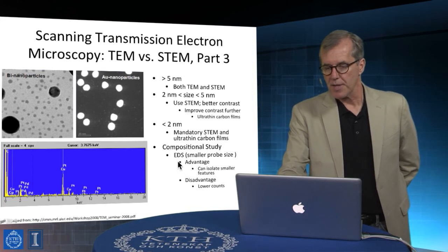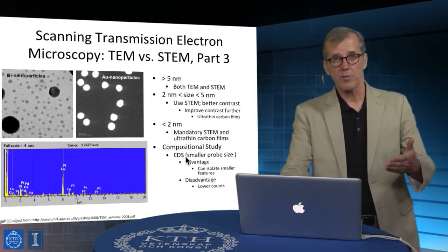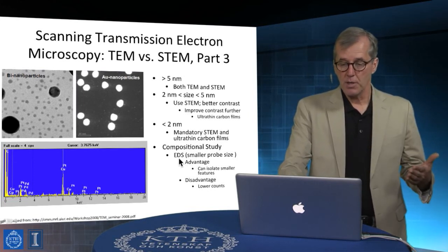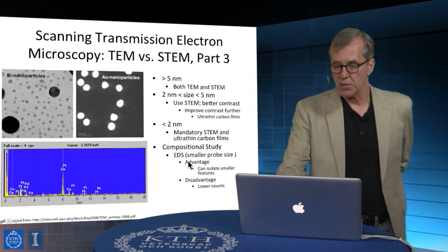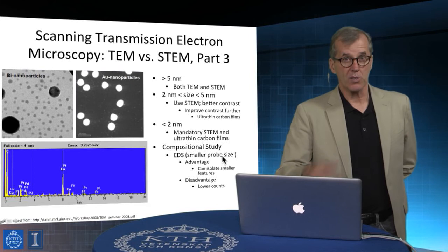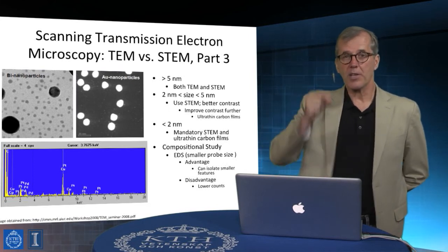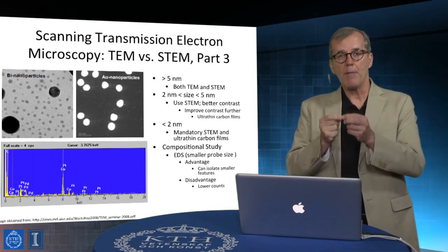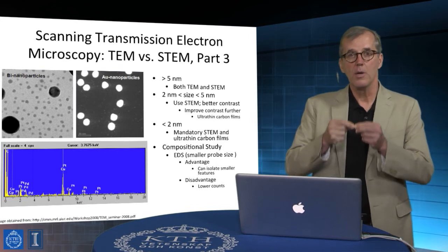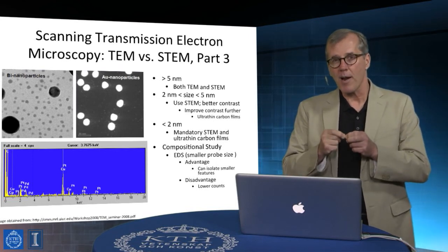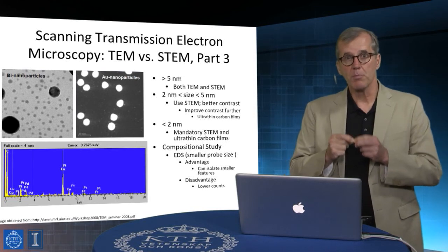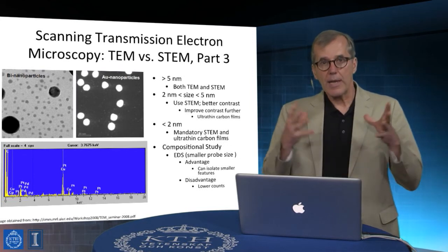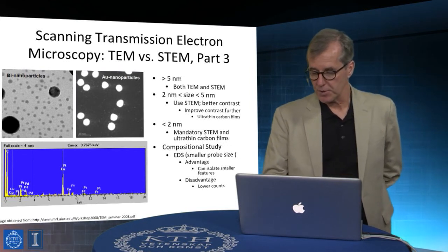And the other part is that if we couple this to other forms of measurement, for example, EELS measurements or X-ray emission measurements for chemical speciation, having small probe sizes is also quite empowering. So we can do X-ray measurements, and now we don't have an excitation volume because the sample's very thin, and we have an atomic resolution probe. We can basically do X-ray measurements that are very proximate to an extremely small probe diameter, right? And so that actually becomes a way of doing nanoscale measurements of chemical composition.